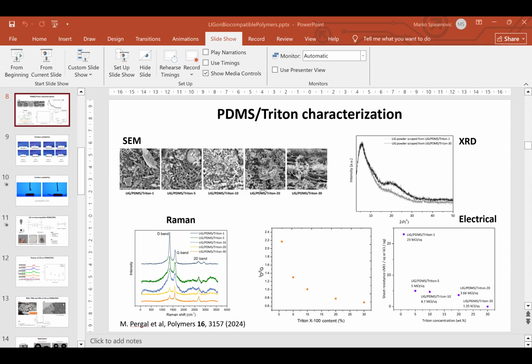But as you add more Triton, the intensity of the defect peak goes down, and that's shown in the middle image. You see that the ratio of the intensities of the D peak to the G peak goes down as you add more Triton. But still, this is not something you can use as an electrode. The final sheet resistance is on the order of a kilo ohm per square. But we found that in general for any type of graphene-based device, not just LIG, but we also do liquid phase exfoliation. We found that if the graphene has around a kilo ohm to a few kilo ohm per square sheet resistance, it actually makes for a better sensor than those that have very low. I'm talking about chemical sensors, yeah, than those that have very low sheet resistance.